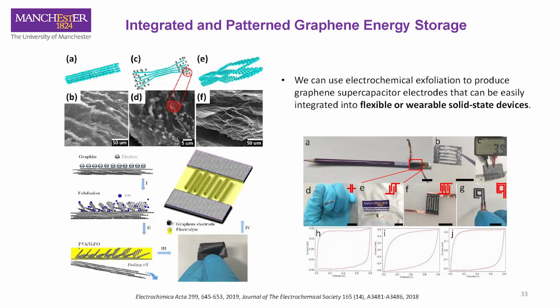So one of the ways we can set about preventing this restacking is taking that material, exfoliating, and leaving it on a foil. So essentially a device like this, where you've got a graphite foil, you're exfoliating the surface of it to get this really nice high surface area. You then backfill that with your electrolyte. In this case, it's a polymer electrolyte. So now you've got a nice solid state flexible device, which you could, say, integrate into biosensors, into clothing. You could have it on fabrics, whatever it may be. And you can get these flexible and wearable solid state devices.